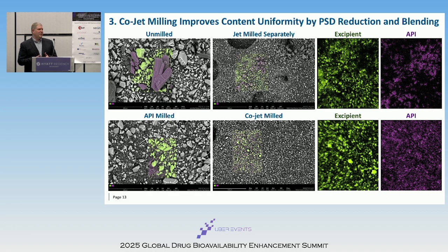A lot of times people just focus on the API and micronize it and then tumble to blend. But you can still see on the bottom left that you see API rich and poor domains where the blending isn't uniform. Oftentimes people will jet mill the material separately, then blend. This could have flow challenges. And the blends you can see on the top right, which is excipient and the API. So you see black areas on the green and the purple images where basically you're not fully mixed yet.